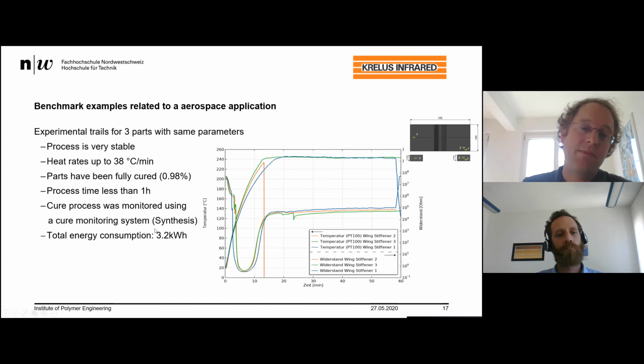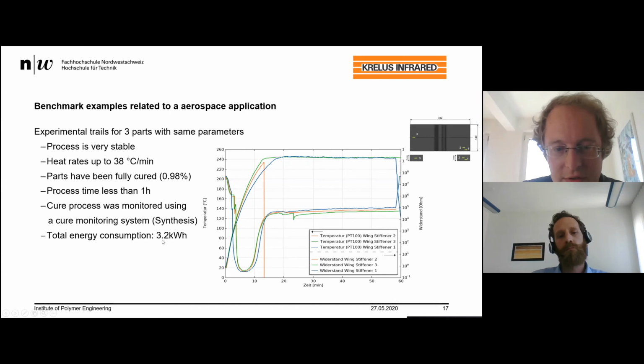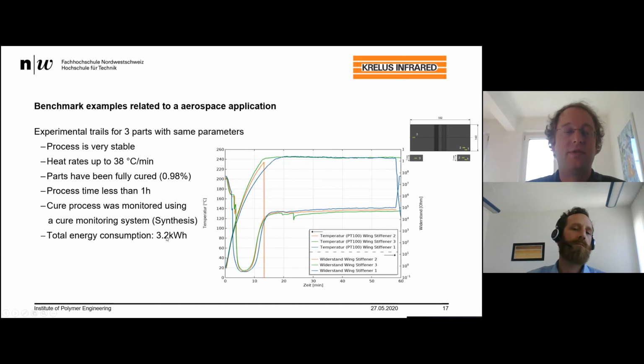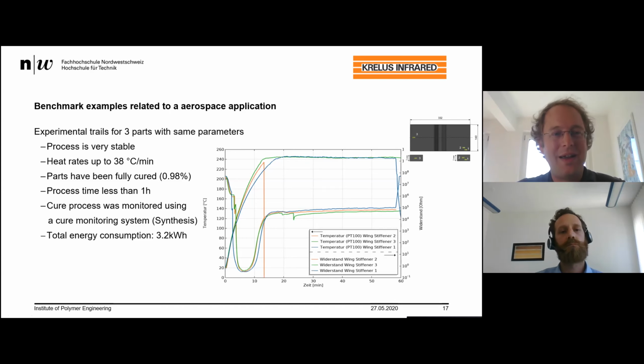So, and at the same time, we have a total energy consumption of 3.2 kilowatt hours. So, and if you think now, if you multiply this by the cost of 1 kilowatt hour, which is around 30 cents, you know how much energy you have applied to cure this part. So in comparison to an autoclave, you can imagine, or later I will come back to this issue.